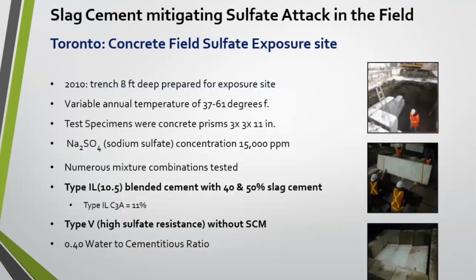So I did want to show you some examples here of exposure sites. This one is from Toronto, 2010. There was an 8-foot deep trench, basically, where these samples were going to be kept, with variable annual temperature between 37 and 61 degrees Fahrenheit. They were put in a sodium sulfate concentration of 15,000 parts per million.